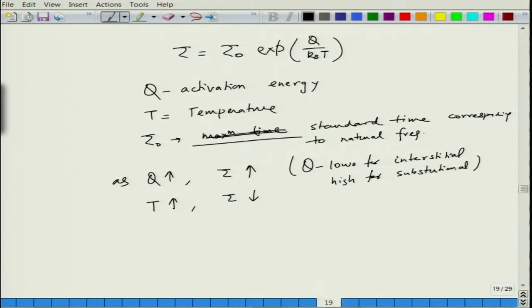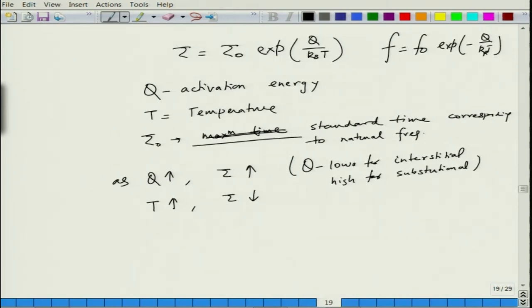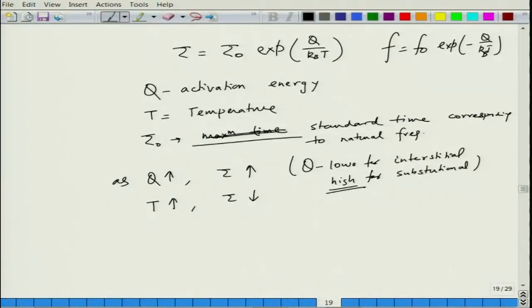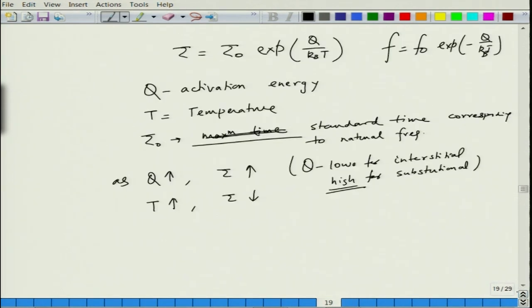For an interstitial atom q is lower, but for a substitutional atom q is higher — because interstitial atoms are smaller and do not need to dilate the lattice as much. As a result, you operate at lower frequencies for bigger atoms. In the frequency domain this corresponds to f = f_0 × exp(−q / kT). When you increase temperature, tau decreases because temperature increases mobility, so atoms diffuse faster at higher temperatures. This is the phenomenon of relaxation in materials showing anelasticity.